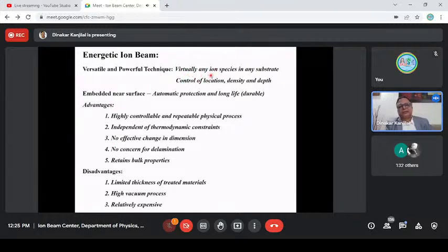As soon as you give energy to the ion or atom, it goes to a range which can be calculated, and it can be checked also. It matches. Calculation today is reasonably accurate, within 1 to 5%, sometimes maybe 7% accuracy depending on the system. You can place them close to the atomic site where you want them. So this is highly controllable.